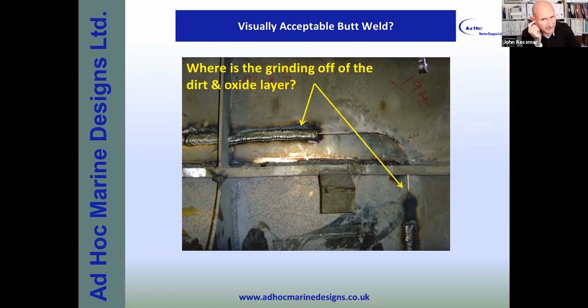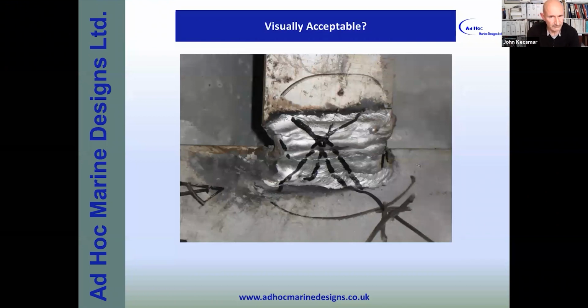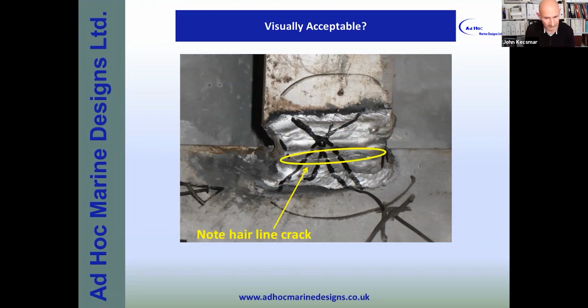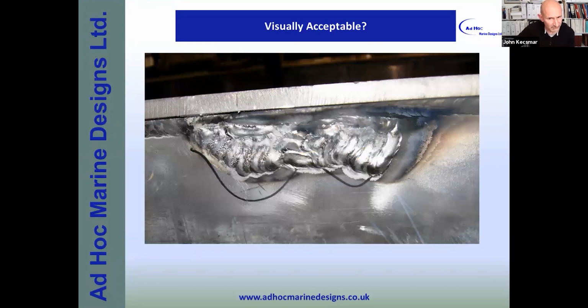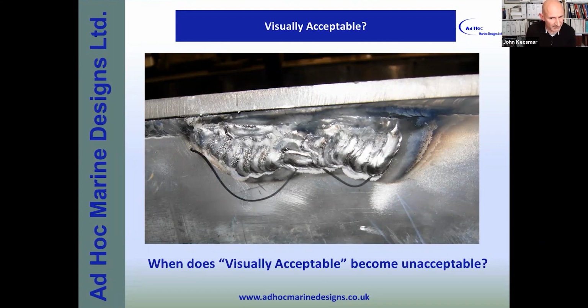And then, what about this? Where is the grinding off of the dirt and the oxide layer? Why hasn't the welder stopped to think, is this something I should do? Ah, it doesn't matter. It's built to class, it should be all right. And what about this? You've got a butting of a rebar into another one, and it's missed. So the welder decided to just fill it with lots of weld. And surprise, surprise, because there's so much weld there, as it cools, it's shrinking. As it's shrinking, you might just make out there's a hairline crack there. And what about this? This is monstrous, utterly appalling. How on earth this is allowed to continue is beyond me. So when does visually acceptable become unacceptable?